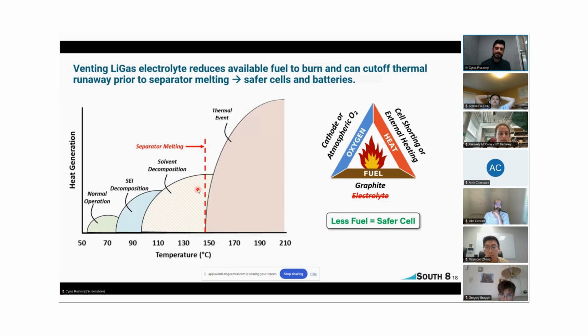With the liquefied gas electrolyte, we have a really unique capability. If we're able to vent that cell of all of our electrolytes right around 90 or 100 degrees Celsius, we remove a lot of that fuel for that reaction and shut down ionic conductivity. By shutting down ionic conductivity, we can actually stop the temperature increase due to all those exothermic reactions and really prevent a lot of these thermal events from occurring.